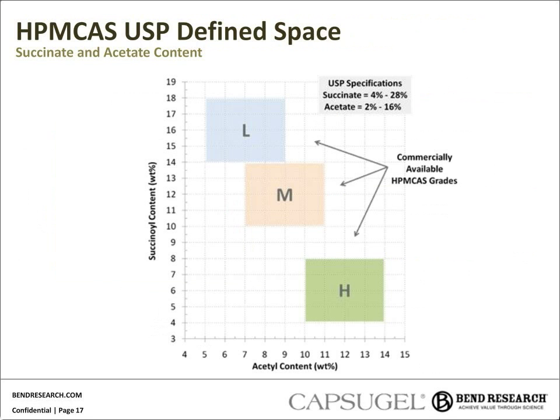As David called out, there are many polymers that are used for dispersions. We commonly use HPMCAS because it's a primary example of a precipitation inhibiting polymer. But the properties of HPMCAS across compendial space, as shown by this whole graph, can vary widely. There are 3 nominal grades that are sold, as identified by the L, M, and H boxes here. But compendial space actually allows a much wider understanding of how your drug interacts with that polymer. And almost in a QbD sense, you can tune your polymer tenets, whether that's performance or stability, based on using different polymers.